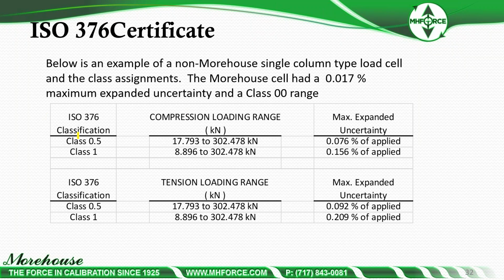Trying to explain with that range there, the classification and some of the other stuff that's going on. So class half in this situation was 17.793 to 302.478 kilonewtons with a max expanded uncertainty 0.076. But then if you look at class 1, the class 1 loading range is greater. This instrument can be used lower, at lower capacities if they meet class 1, and at higher capacities for class half. And if you look at the max expanded uncertainties, 0.076, 0.156, 0.092 in tension, and 0.209